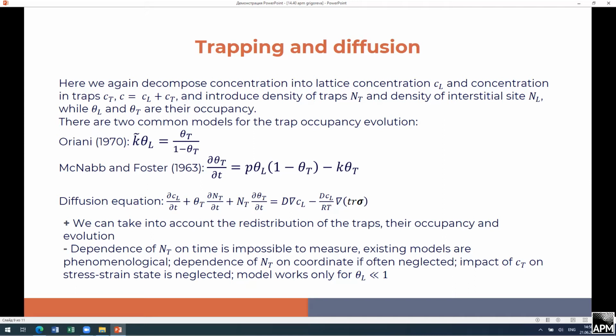So the good thing of this model is that we can take into account the redistribution of traps and see how it changes with time. But the bad thing is that for this model, we should know the distribution and the time dependence of the density of traps and interstitial sites. Therefore, we should measure it, but we still don't have any experimental techniques or ideas or models to measure it.